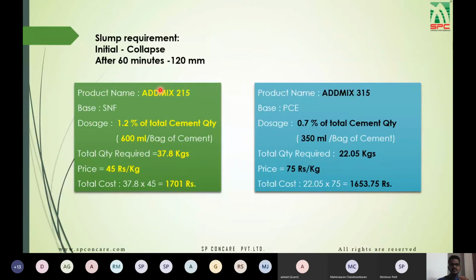For the SNF based admixture, admixture 215, we consider a dosage of 1.2% of total cement quantity, or we can say 600 ml per bag of cement. On the other hand, the dosage of 315 is 0.7% of total cement quantity, that is 350 ml per bag of cement. So the total quantity, 1.2% of 3150, comes to around 37.8 kgs. For 315 it came to 22.05 kgs. The basic retailing price of admixture 215, excluding GST, is 45 rupees per kg, whereas admixture 315 is 75 rupees per kg.